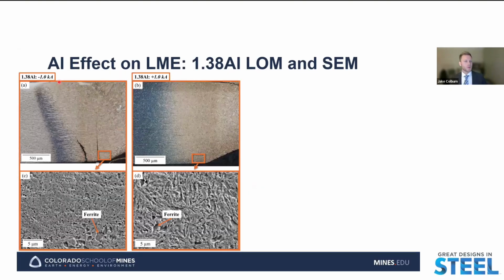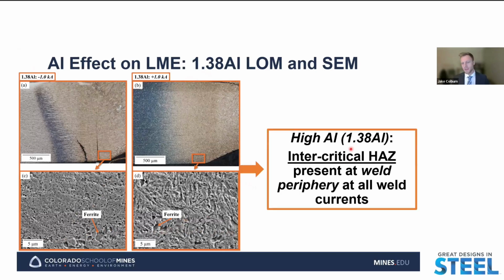But then when we compare that to the high aluminum alloy, and here again looking at the optical micrographs of the high aluminum alloy welded at 1 kiloamp below and above the expulsion current, we see that at the weld shoulder, there are still noticeable amounts of ferrite present in the microstructure. And so we can describe this as being part of the intercritical heat affected zone in the weld periphery.